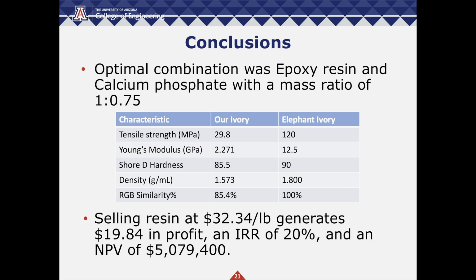In conclusion, the optimal combination was epoxy resin mixed with calcium phosphate with a 1:0.75 mass ratio. This mixture resulted in the closest sample to resemble the material characteristics of ivory, such as tensile strength, hardness, and density. Selling resin at $32.34 a pound generates $19.84 in profit, a rate of return of 20%, and a net present value of $5.1 million.